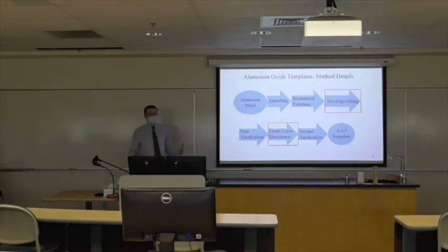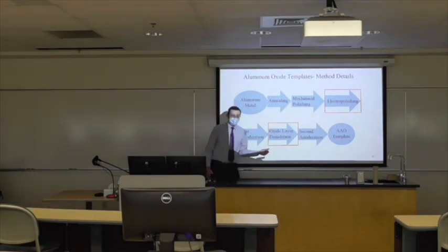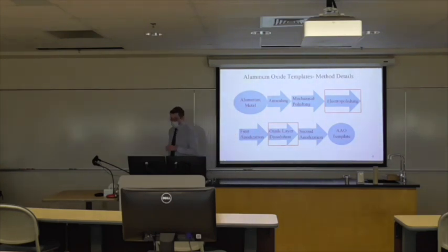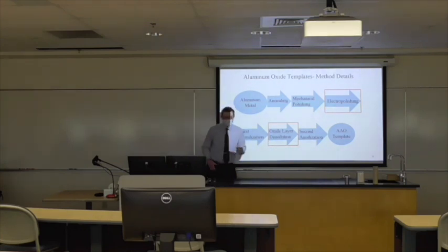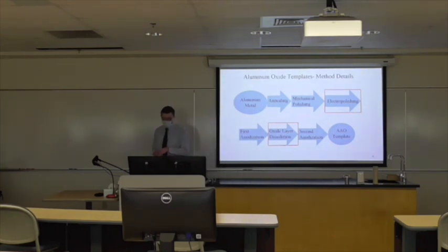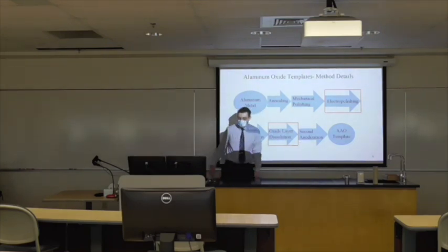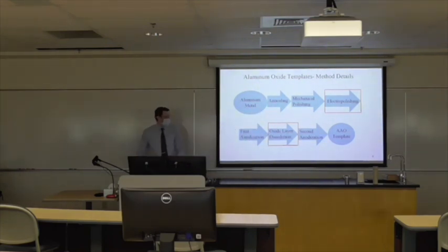Now here's another issue as far as green chemistry, because this is generally done using chromic acid, which is not environmentally great. Chromic acid contains hexavalent chromium, which is an environmental hazard, a pretty serious one. So we're concerned about that when we're considering how we make these templates. And then you use a second anodization process, which would be largely identical to the first, and you're left with your aluminum oxide template.